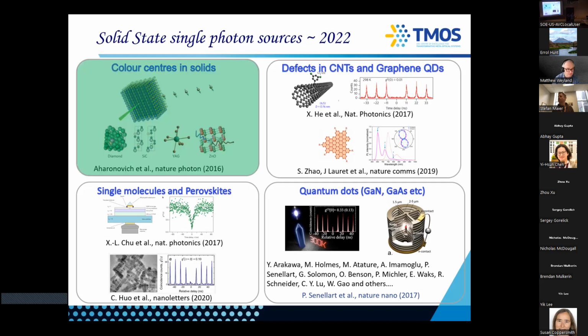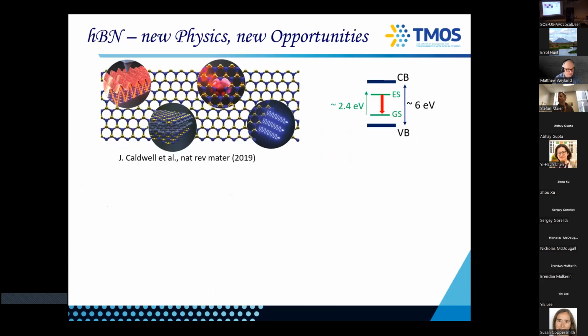And of course, our interest is in the color centers, which are these deep defects within the band. And so when you look at which material to choose, diamond has about a 5 eV bandgap, but you can also choose hexagonal boron nitride, and it has a 6 eV bandgap. Actually, what is very interesting about hexagonal boron nitride is that the bandgap was always thought to be direct, but actually it is an indirect bandgap material.